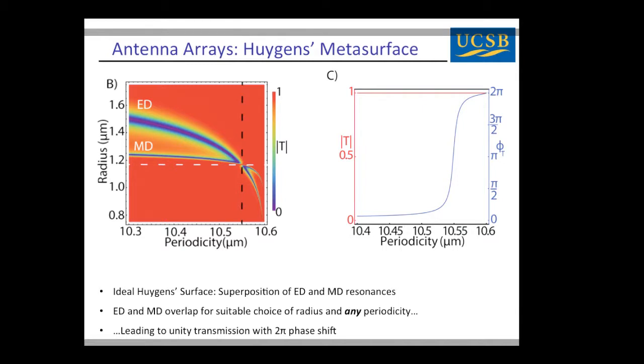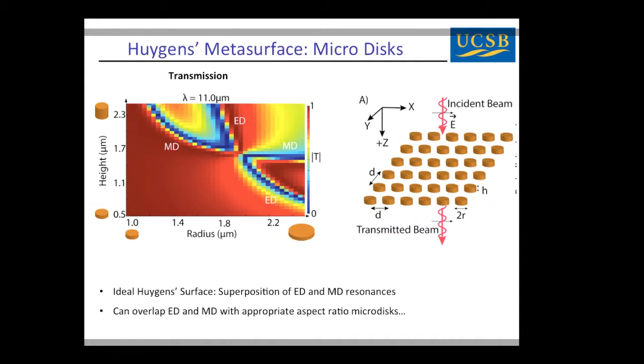but for making a phased array, you don't really want to control periodicity. Again, what I said is that introducing free carriers is effectively like changing the size, okay? Or like this black line cut over here. So instead of looking at spherical particles, what we want to do is design a resonator where both the magnetic and electric dipole modes are at their peak resonance at the same time. So instead, I'm going to talk about disk arrays, right, or these top-down fabricated truncated cylinder structures. And now we have an extra degree of freedom.